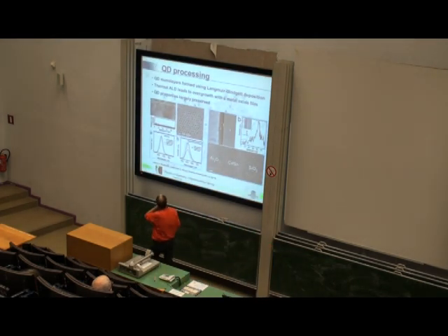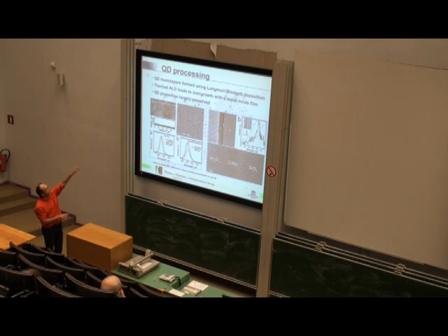This is work we did together with Christophe Detavernier, where we worked with these Langmuir-Blodgett films on a substrate, and then you can use atomic layer deposition, ALD, to overgrow such a layer of quantum dots by, for instance, a metal oxide. In this way, you can go to a kind of material, shown here by the black line, where you have these nanocrystals embedded as a thin film, a monolayer, inside a solid matrix. And that's the way we work on the processing of these materials.